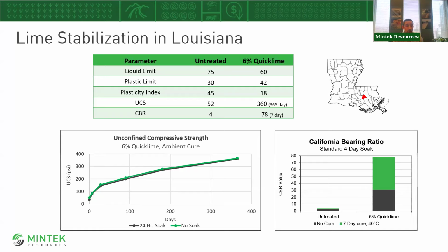And that's not to say that before that, modification didn't help us get on that soil and keep construction activities happening. On the right side, CBR, untreated, super low. Don't know the value. Probably looks like a 5 or a 4. Then no cure, so essentially only from modification alone, getting up to already 30. So nice and solid there. But the higher green CBR value, once we've cured it to show what it does over time, is another testament to lime gaining strength for true stabilization.